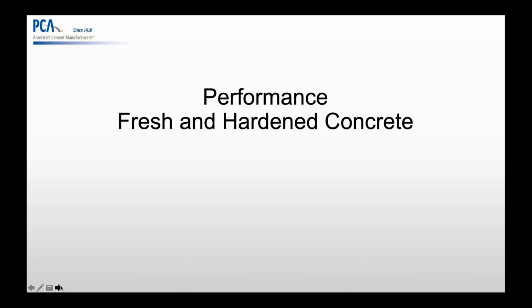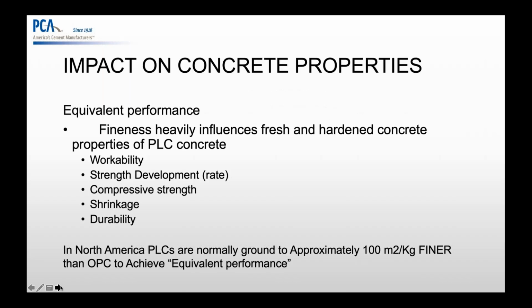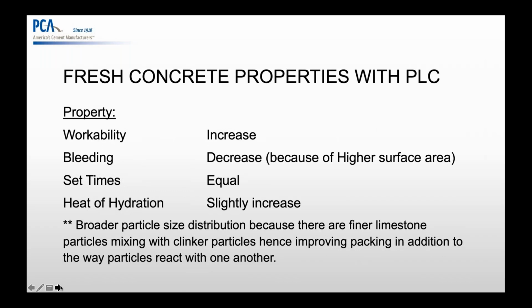Let's move on to performance of fresh and hardened concrete. As stated, the fineness of the cement counts for a lot. It will influence properties like workability, compressive strength, shrinkage, and durability. As far as durability goes, it's an extremely important item for the DOTs, especially for governmental projects. The ACI 318 specifies durability requirements such as external sulfate attack, whether it's from your soils, seawater, wastewater, that can be mitigated with SCMs, the chloride ingress, and the freeze-thaw cycle. So those items are tested and were tested in the past, and the PLCs meet the requirements of all those items in the durability.